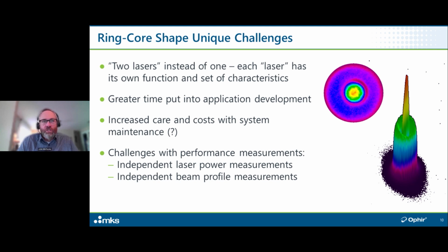You've got the ring, which is a relatively larger beam size, a relatively lower intensity, and hopefully you see that with these two images, both the 2D and the 3D images. The ring is just operating at a lower intensity. It may be of a higher power, but it's at a lower power density. Versus the core, where you have a relatively smaller spot size, which is going to result in a relatively higher power density. Two very different power densities, two very different results in how this laser is processing the material. That's going to come into play when we talk later in the webinar about power density, because it's a really good illustration of that fact.